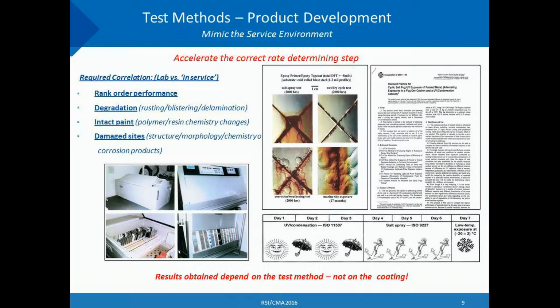But if you combine the corrosion wet-dry cycles with UV weathering characteristics, this is what you get. This is the ASTM D5894 test. And you can get a sense that this procedure mimics what's really happening outside quite closely. And in a lot of work that was done, the corrosion products match the chemical composition of corrosion products in the scribes. These blisters are filled with solidified corrosion products, just like these.